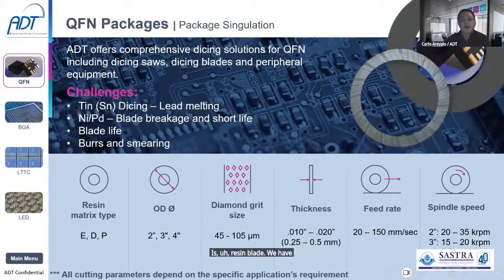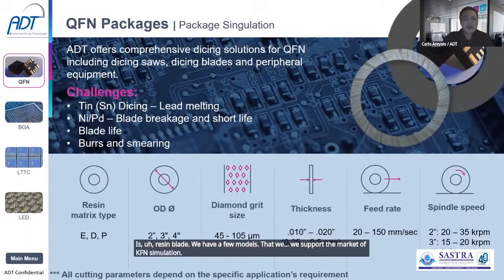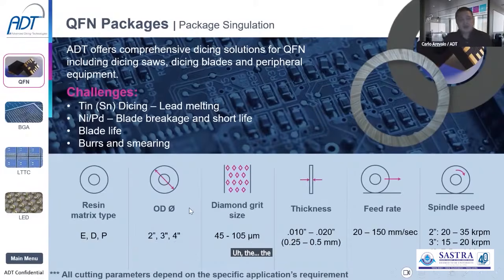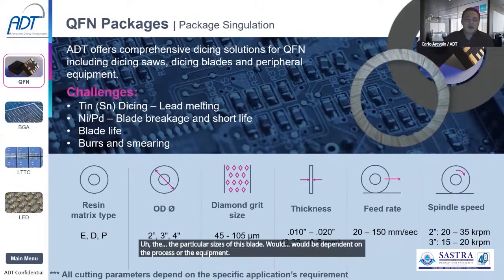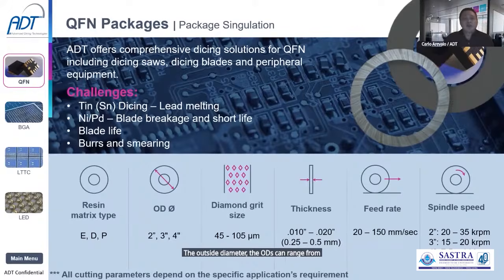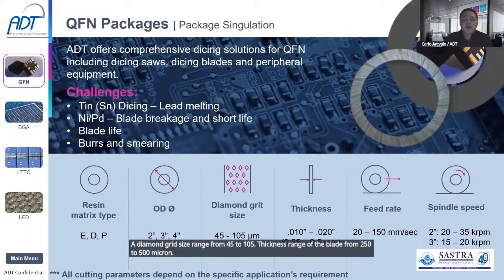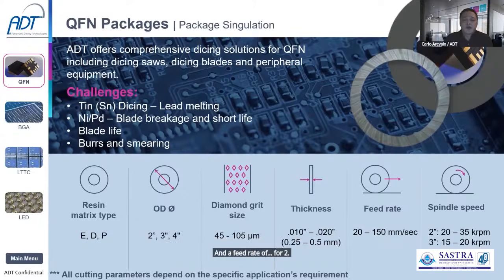We have a few models that we support the market of QFN singulation. The particular sizes of this blade would be dependent on the process or the equipment. The outside diameter, the ODs, can range from 2, 3, or 4 inches. The diamond grit size ranges from 45 to 105. Thickness range of the blade is from 250 to 500 micron, and a feed rate of 20 to 150 millimeter per second. Spindle speed will also be dependent on what blade diameter or what equipment you are using. So these are all optimized during the development of the process.